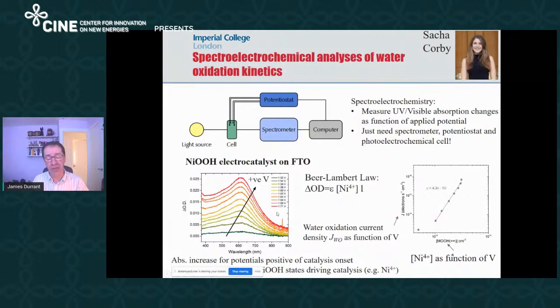In terms of optical spectroscopy, it's well understood that if you've got an optical signal, you could turn it to a population by applying the Beer-Lambert law. And if you measure the current density, which corresponds to water oxidation at the same time, you can plot the current density, the water oxidation flux, versus the density of charges driving that current. And in this case, this is a log-log plot. The gradient is 4, which means that every time you double the amount of nickel 4+ in the system, the rate of reaction goes up by 2 to the power 4, by 16.